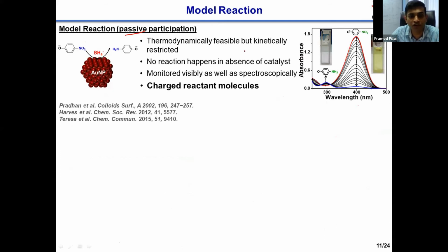This is a model reaction for many reasons. Some of them are that this reaction will only happen in the presence of a catalyst. That means if there is no catalyst, this reaction will not happen. And the mechanism of this reaction is well understood. And here again, the molecules are charged. If you see under reaction conditions, there is a lot of negative charge on the reactant. So we can use our electrostatic interactions to govern the catalysis. Another important fact is that you can study this catalysis easily by spectroscopic techniques, because the starting material has a yellow color, which will decrease when it converts into the product. So it can be easily monitored using spectroscopic studies.